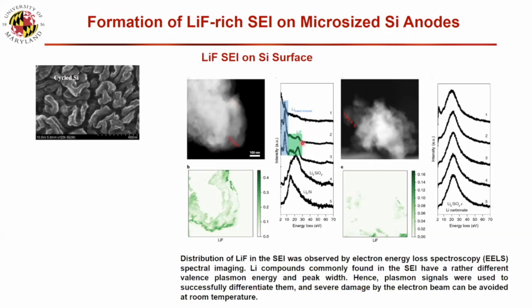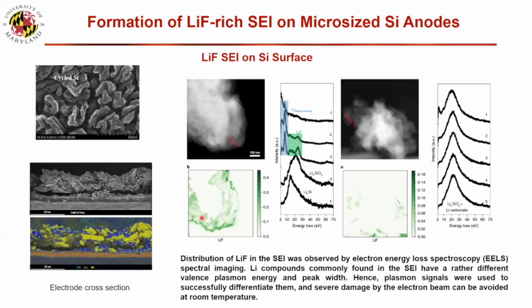And then we use the EELS to identify, and we check this, one, two, three, four, five, and then we use the EELS mapping. We see at the surface is the polymer, and in the second layer near the surface we have a lithium fluoride, and inside is lithium silicon. So we really see clearly the lithium fluoride. And if you use traditional electrolytes, you never see a clear lithium fluoride surface layer. They always mix with the carbon, the polymer. So this identifies that we really form lithium fluoride on the surface using THF solvent.